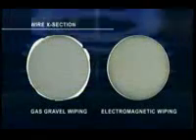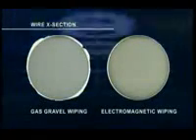The wire emerges vertically from the zinc bath and is immediately wiped. The coating thickness is achieved by using one of three wiping systems. The electromagnetic wipe is a new wiping system developed in-house and now being sold around the world. It delivers a more precise, consistent and controllable wiping process with less variation in coat weight. A gas jet wipe is also used for achieving heavy galvanized coat weights. The pad wipe is used to remove excess free zinc for standard and lower galvanized coat weights.